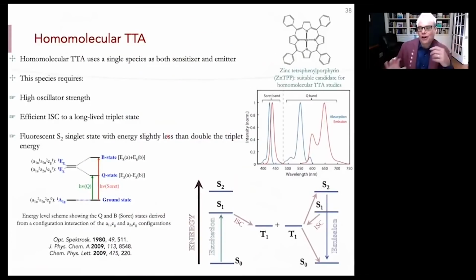So here's some of the concepts. Again, nothing has changed except that the acceptor annihilator is also the sensitizer. That's the only thing that's changed. And this was first developed by the Soviet group in 1980. So these are metallated porphyrins, but they're magnesium porphyrins. But then more recently, especially with zinc TPP, this has really been pioneered by Ron Steer up in Canada. But really showing the fact that you can do triplet-triplet annihilation in the porphyrin itself, which for many of us that do triplet annihilation photochemistry, we all know that there's a background porphyrin annihilation going on that we always ignore. And that's one of the things that limits the efficiency.